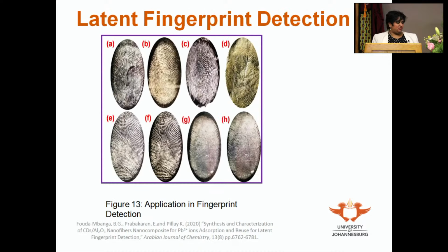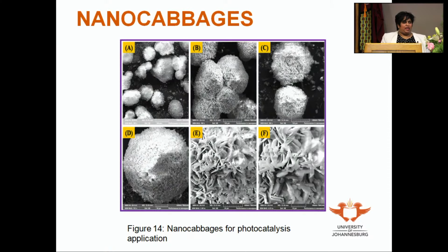So this just shows you some diagrams in which we were able to capture the fingerprint images on different surfaces to prove that the presence of lead was significant in terms of helping us identify the fingerprints. Okay, so I've spoken enough about how we remove pollutants by adsorption.